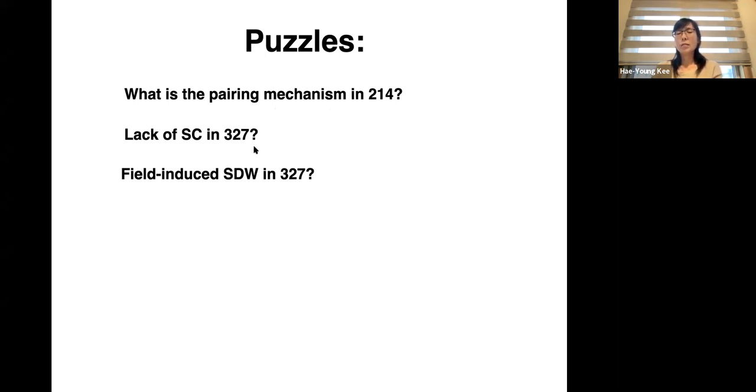Remember that I said this was initiated by high Tc. In a high Tc compound, whether you have a 214, or bilayers, or even chains, they all appear to have very robust superconductivity, while here it is very, very sensitive to any changes. And that's what led people to think that this might be a triplet as well, in addition to the fact that the 113 compound, which is a three-dimensional version of it, is a ferromagnetic metal.